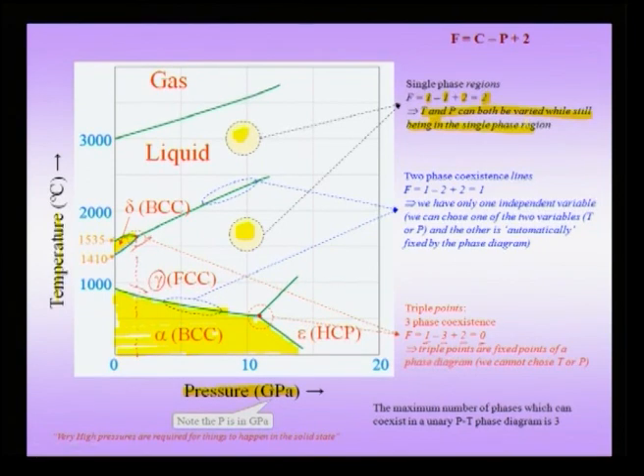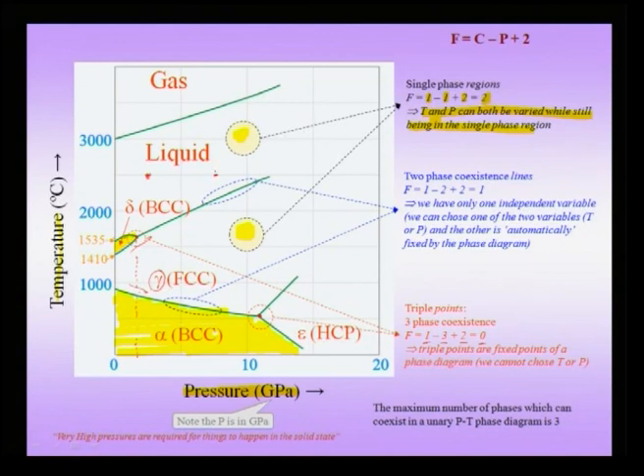For instance, a point where the pressure is approximately 2.5 GPa and temperature is 2500°C, and also a point where temperature is 2500°C but pressure is approximately 7.5 GPa, are both in the single phase liquid field. That means in these regions I can vary both temperature and pressure and still remain in the single phase field — until I hit the boundaries where the single phase region ends.